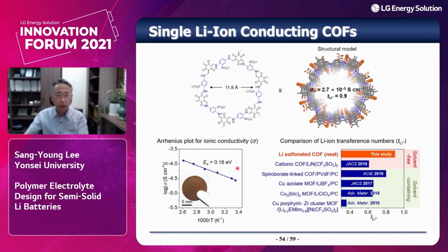Here is the chemical structure we have designed. The pore size is approximately 10 angstrom, and the ionic conductivity is not so high. However, this is meaningful without any solvent, and we have obtained a cation transfer number of almost 0.9. And the more important one is the activation energy, which is very low. That means this framework structure with directional ionic channels can accelerate ion transport through the channels.